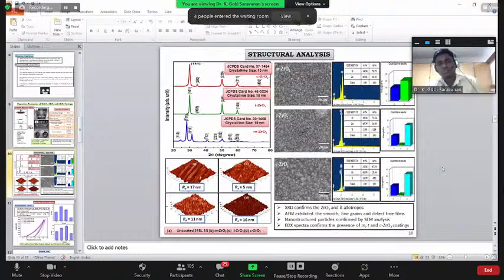After that, we studied XRD and AFM for microstructure as well as roughness. From SEM it is indicated that the film is nanostructured. This is a 200 nanometer scale length, and the particle size is approximately 20 to 30 nanometer. From that we can conclude that we have obtained nanostructured zirconium oxide.